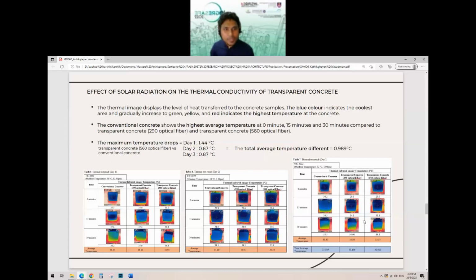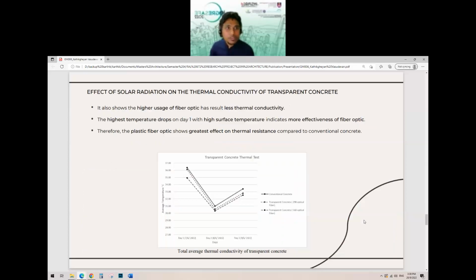The maximum temperature drop for day 1 is 1.44 Celsius, day 2 is 0.67 Celsius, and day 3 is 0.87 Celsius. The total average temperature difference is 0.989 Celsius. It also shows that higher usage of fiber optic results in less thermal conductivity, and the highest temperature drop on day 1 with high surface temperature indicates the greater effectiveness of the fiber optic. The plastic fiber optic shows the greatest effect on thermal resistance compared to the conventional concrete.